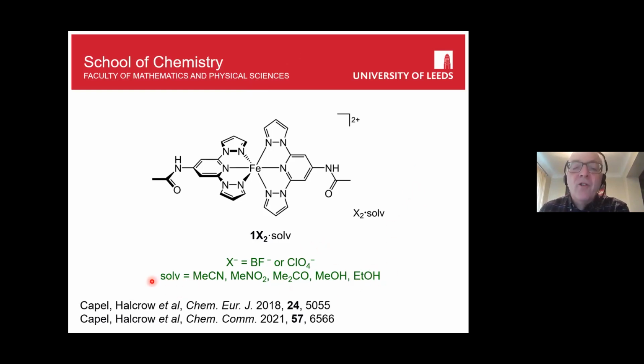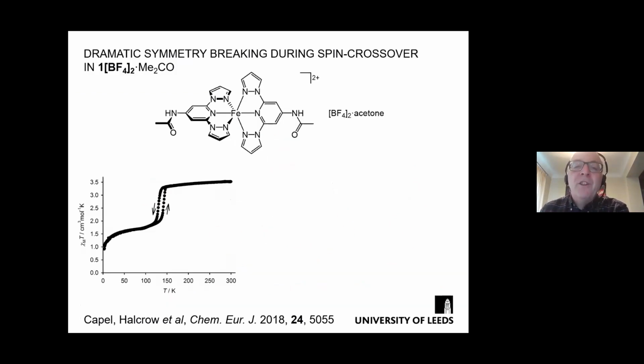So I'm not going to talk about all these different solvates you can make with this compound, just a few of them. And we first published this 3 years ago with the acetone solvate of this complex, which does a thermal spin transition like this, quite abrupt, little bit of hysteresis, to about 50% completeness, and then it stops.